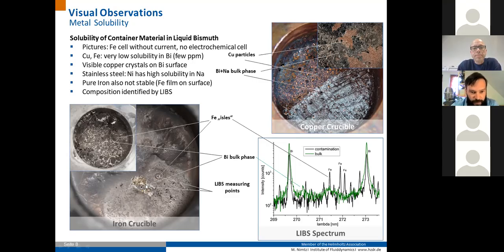Something similar happened with iron, as a pure iron crucible. Here also some iron ions could be detected. We used a LIBS spectrometer for identifying the different constituents of the black or highlighter impurities seen here. We then step by step switched from these cheap materials, copper and iron, to stainless steel and other crucible materials.